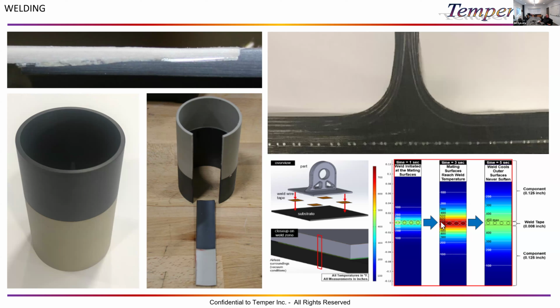And as you can see here, it flash heats. So the wires get very hot, very fast, like in 3 seconds. And what that does is that heats the wires, melts the resin, but doesn't disturb the fibers. You can see here, the fibers are undisturbed.